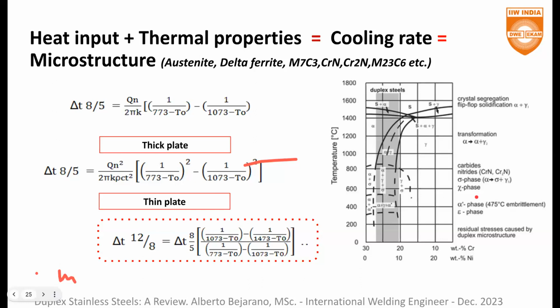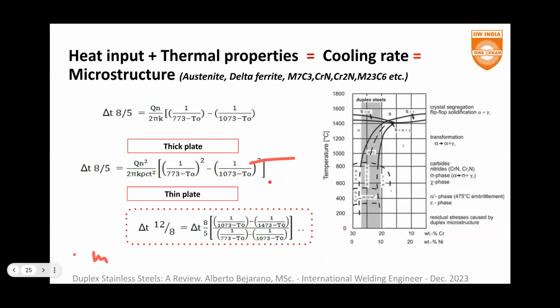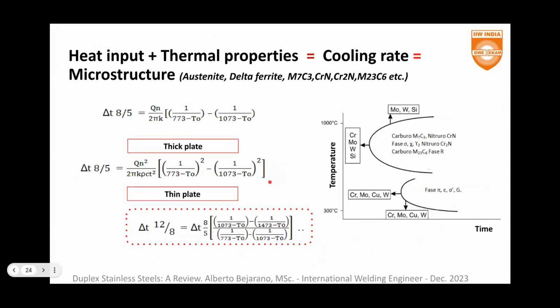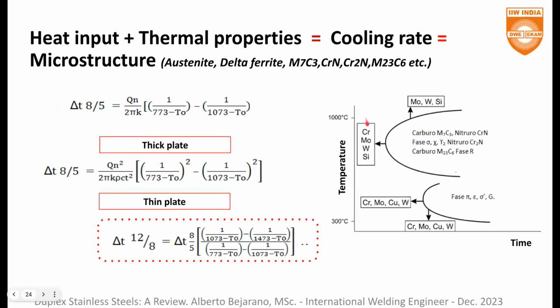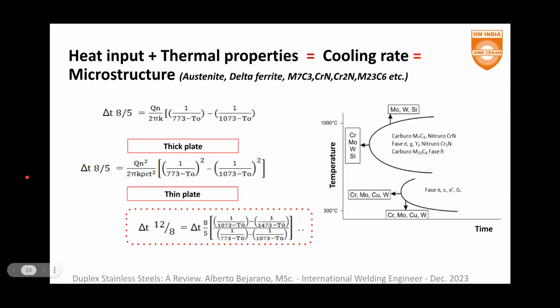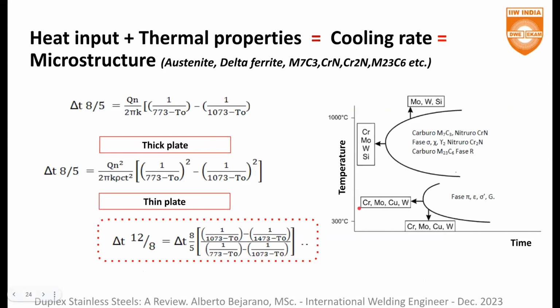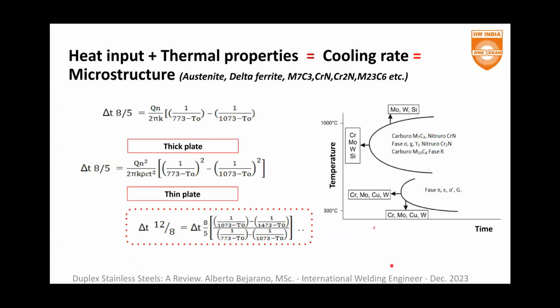Of course, I know you have this information in your mind. We have to consider if we are welding a thick plate or a thin plate. The difference is, if I'm able to weld with just one bead, I'm talking about a thin plate. If not, I'm talking about a thick plate and I need more than one bead. We are talking about a multi-layered joint. Okay, so my idea is to come from liquid and not touch these curves, these noses. It must be enough to produce austenite and must be quick enough not to touch these noses. That's all the clue of this material.